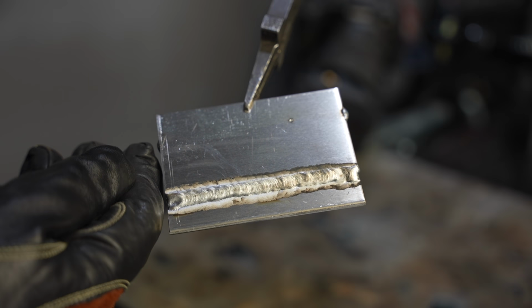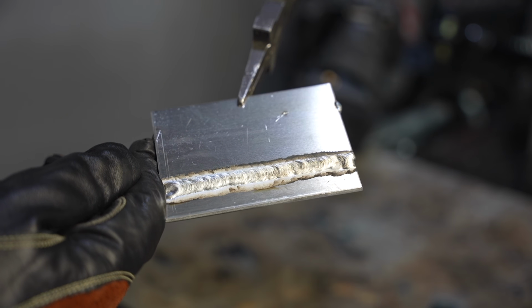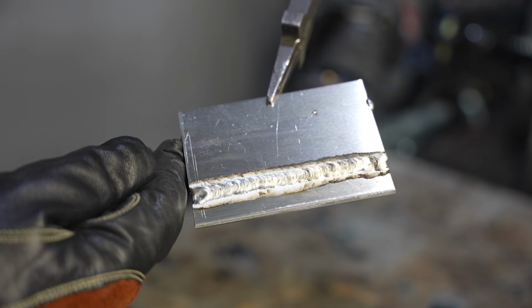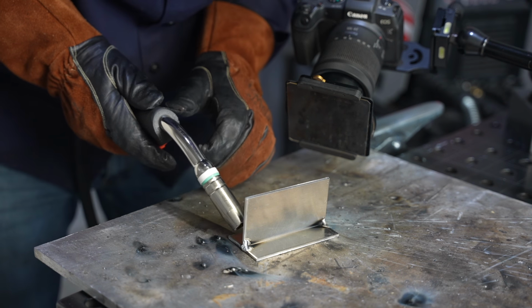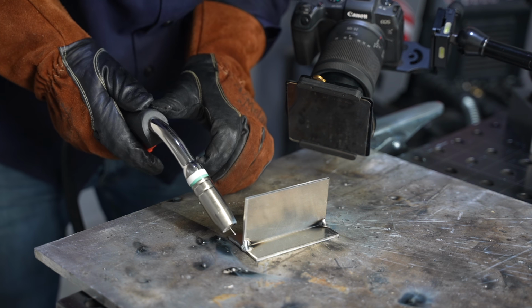And this is great from a productivity perspective, but it can be difficult from a skills perspective. You can see you get a nice smooth weld there. And this is some 1/8 inch thick plate, and in order to get enough amperage, I'm pushing a lot of wire, and so I have to move that quickly.